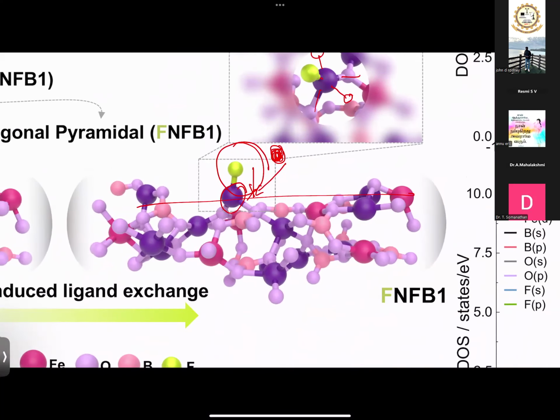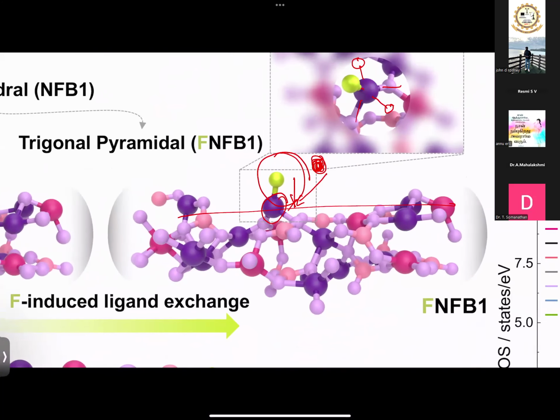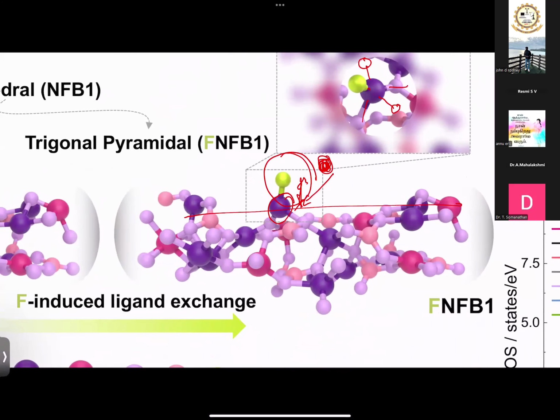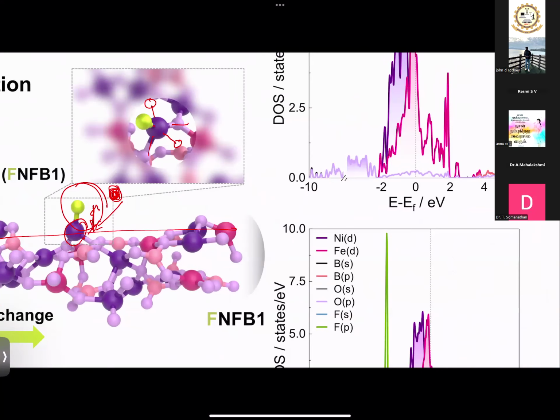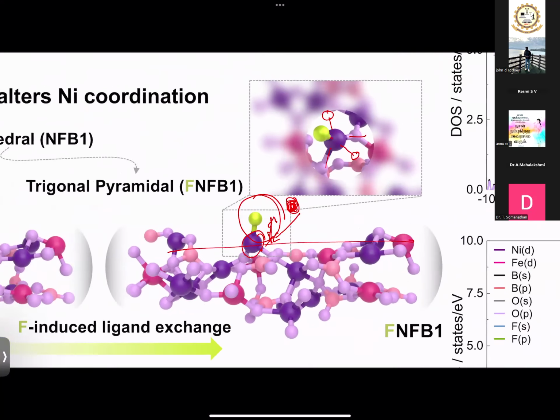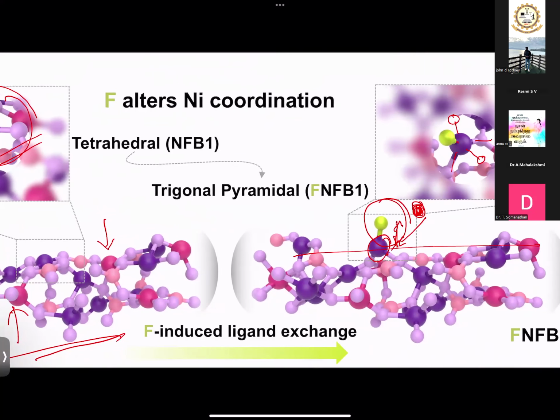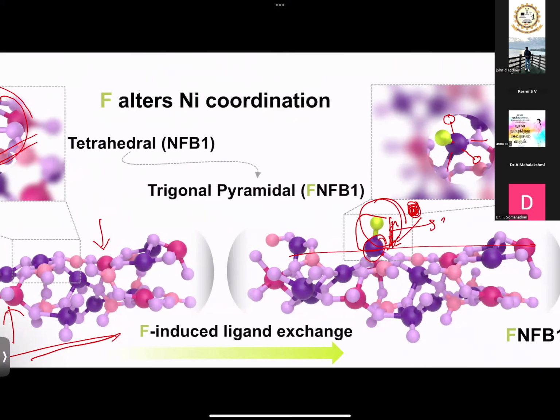nature. So you can see that every single thing that we have experimentally tested and evaluated is being proved over here, stating that because it's being pulled out, this is altering the planes and forming defects, which we saw in the XRD and other things. And this fluorine bonding was checked through XAS, and it's proved over here again. And we can see that the coordination is changed.